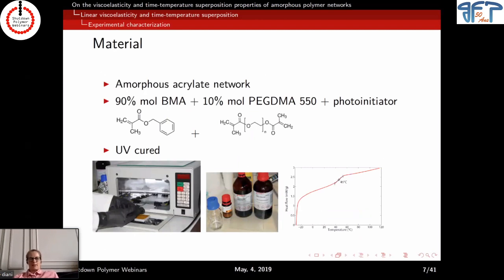Okay, so that's about all the chemistry you're going to see in my presentation, I guess. So we're not chemists at all, but we like to make our own material in the lab to be able to control that and not deal with complex industrial material. So we are making acrylate networks because they're easy to make. So we mix monomers and crosslinkers, and we cure them in a UV chamber. Here you see the students putting the mix in between glass plates. So we end up with plates with constant thickness that we can cut and then test.